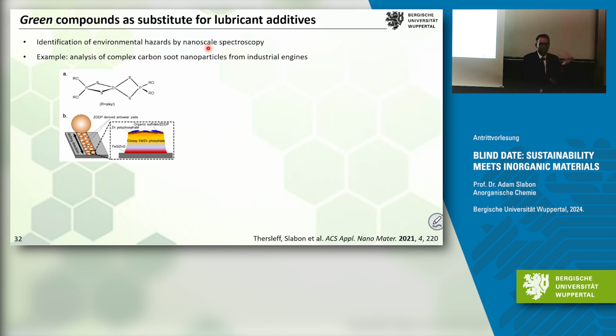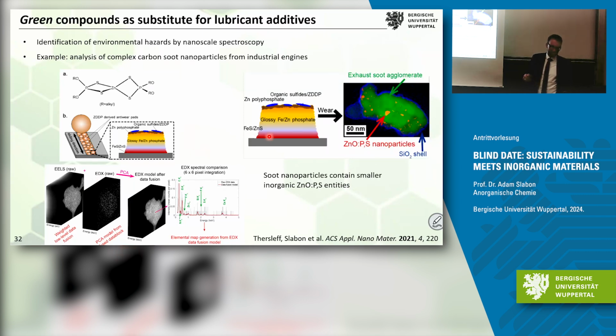What you usually do, you have a reference oil, you have some additives. Maybe you know this compound, ZDDP, ever heard of? It's an additive. This organometallic compound decomposes in operando to a polymeric film on the surface, and then at the end of the life cycle you have some carbon soot particles, and people thought you have this polymer there, it's safe. But if you go for nanoscale spectroscopy in combination with EDX, you see that actually in these carbon soot particles you have zinc oxide particles doped with phosphorus and sulfur.